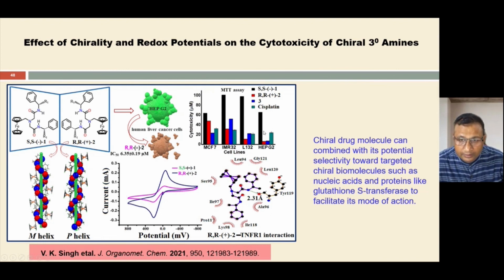As you can see here, the black bar denotes the S enantiomer and the red bar denotes the R enantiomer. So the activity of the R enantiomer is found to be much better than the S enantiomer against all the cell lines. So we have reported the influence of chirality as well as redox potential on the cytotoxic anti-cancer activity of these enantiomers.